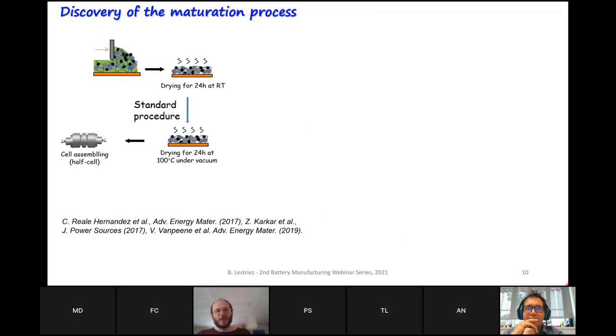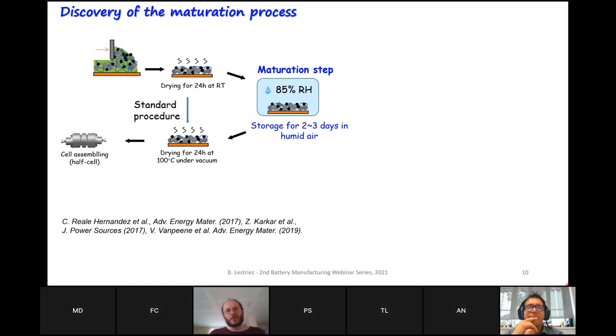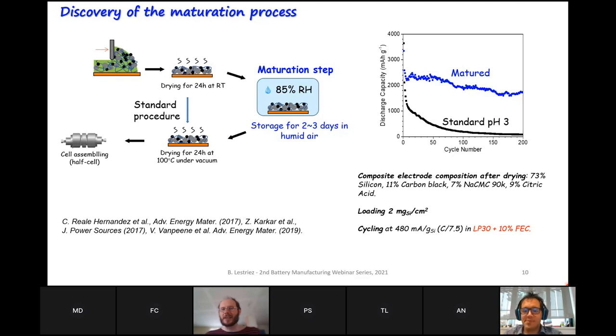Next. And then for this peculiar binder system, carboxymethyl cellulose and citric acid, we discovered a peculiar phenomenon, which we call the maturation process. It consists, after the fabrication of the electrode and the first drying at room temperature, of the exposure of the electrode for a couple of days to humid air before the final drying at high temperature and under vacuum and the battery assembly. Next. And we observed that this maturation really significantly improved the cyclability of silicon-based electrodes